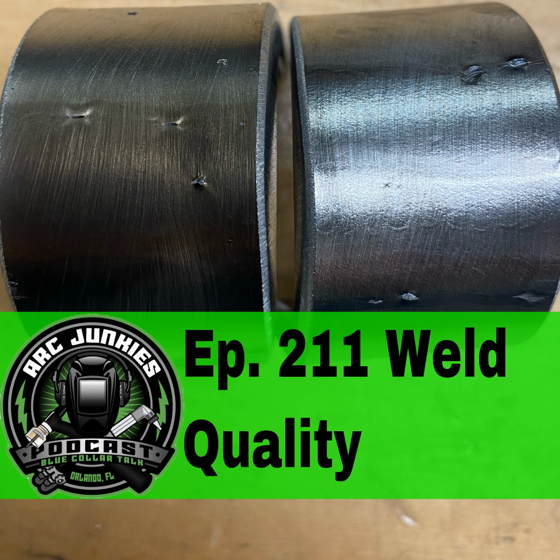Next up is concave root surface, or suckback. Concave root surface is the configuration of a groove weld exhibiting underfill on the root surface. Whether this is on pipe or plate, we're trying to weld the backside of the plate or pipe from the front side. One thing that can cause this is a travel speed that's too fast. Once again, too fast of a travel speed is going to cause us a lot of problems. We got to give time for these things to do their job. We got to give the time for the electrode to cut in and fill and melt and all that good stuff. So if we're going too fast, we can get sucked back.